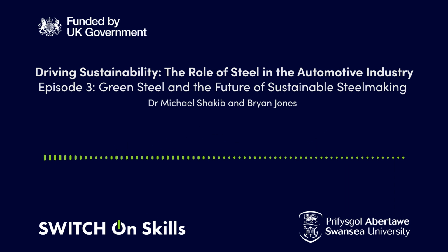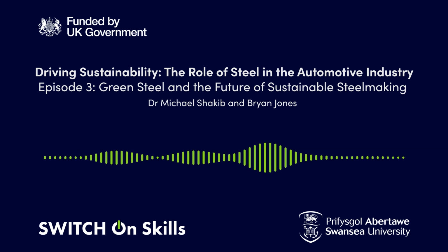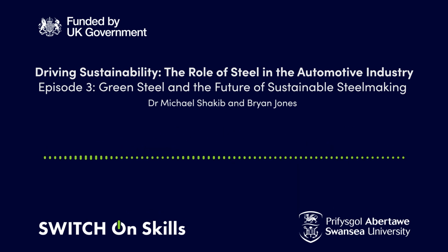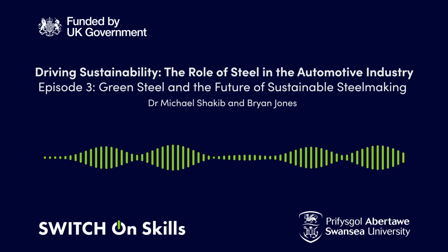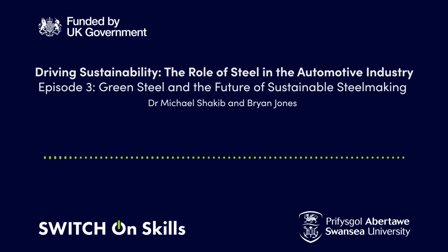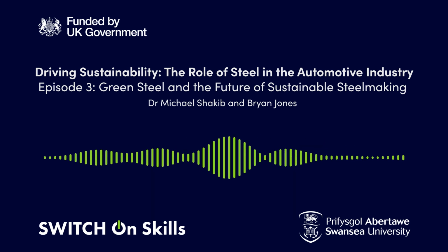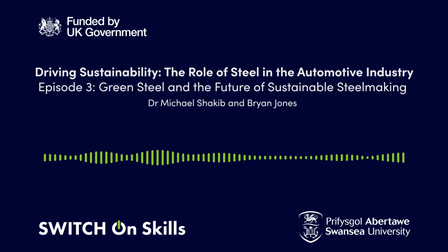That's recycled back to the methane gas reformer, where hydrogen can be added to the natural gas to reduce carbon dioxide emissions. I should also add that there's still a significant amount of carbon present in the product. You're talking about 0.8 to up to 3% of carbon. So as a consequence, you are recycling carbon dioxide back to the methane gas reformer, then there's a reduction in the CO2 emissions from the Midrex process.